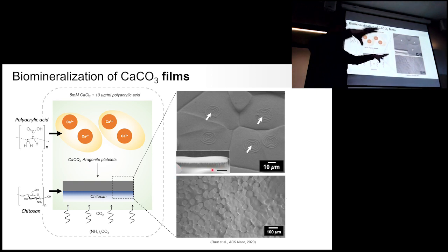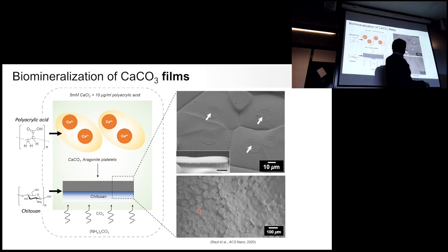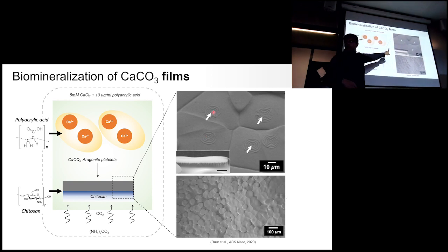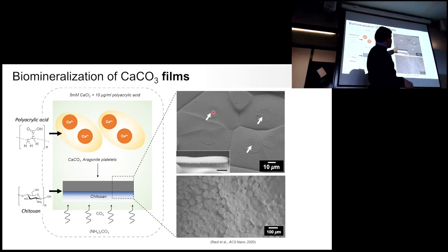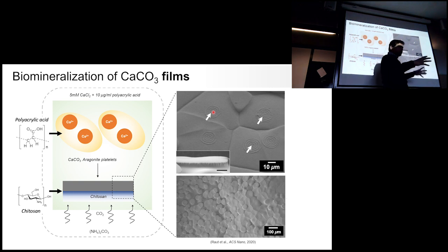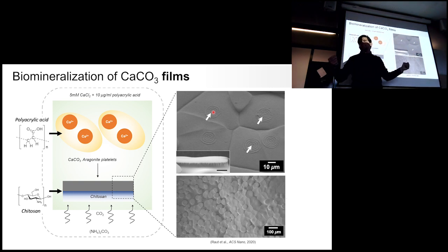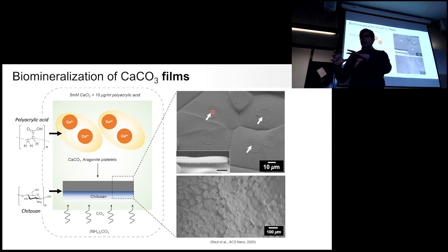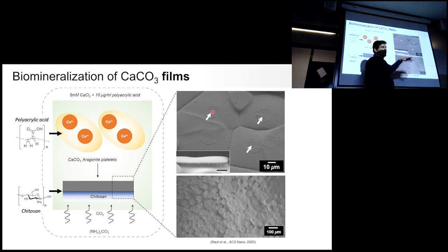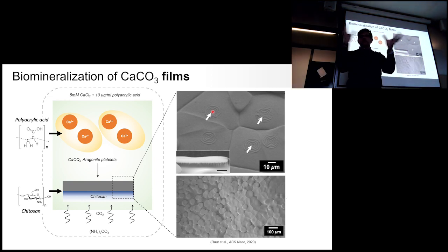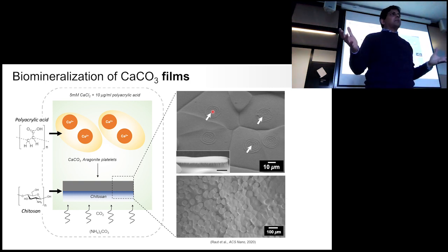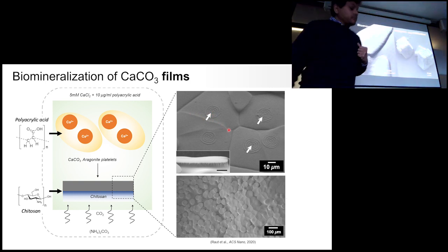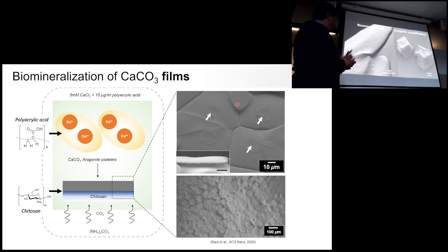And you see here, these are the nucleation centers, and as the crystal grew, it has these sort of footprints of where it started crystallizing, and this is the same kind of structure you see in nacre also. You see in nacre these kind of films forming, growing inside out, and then meeting the next growth front and stopping there, which is why you get what is called the Voronoi patterns of these crystals, a mosaic of calcium carbonate tablets.